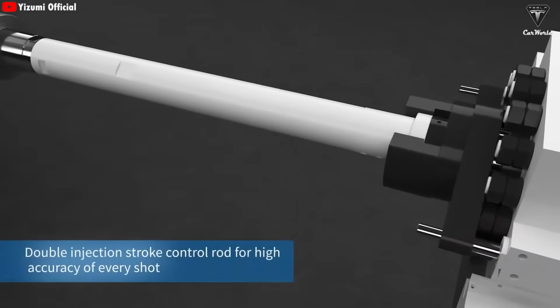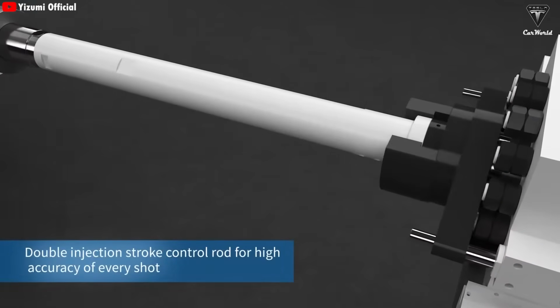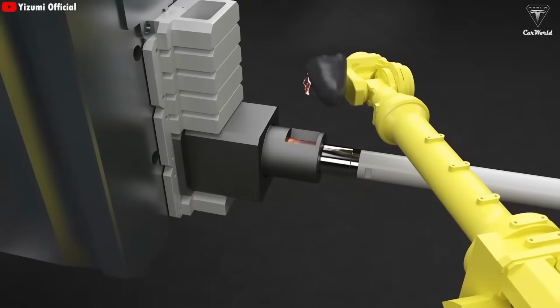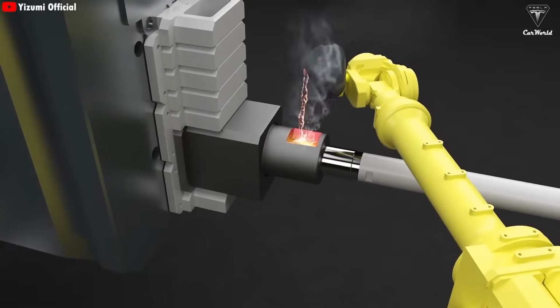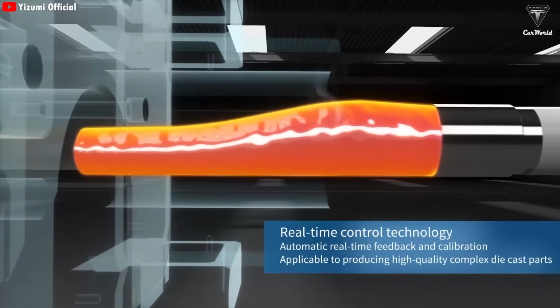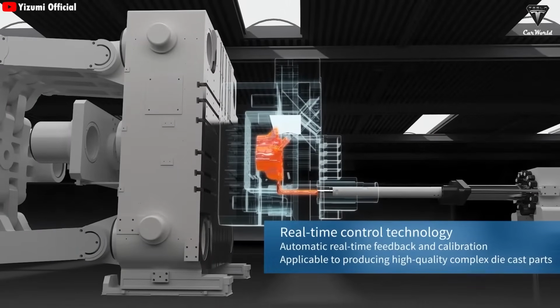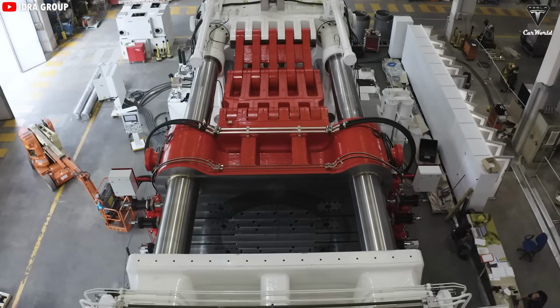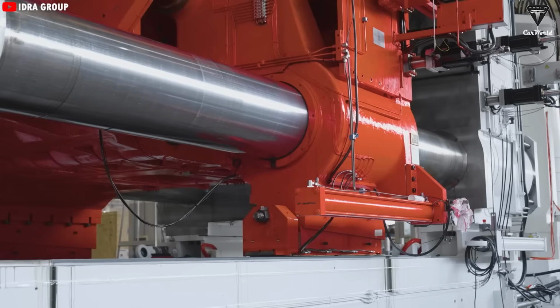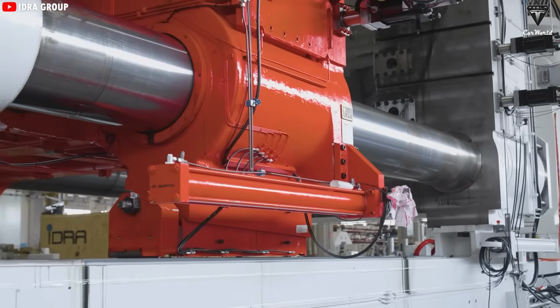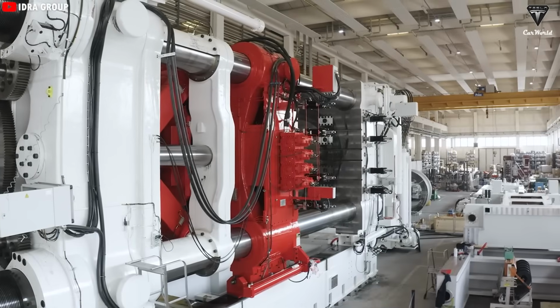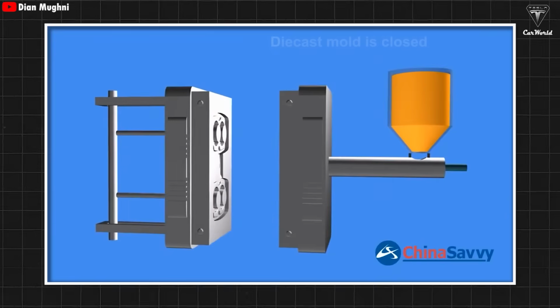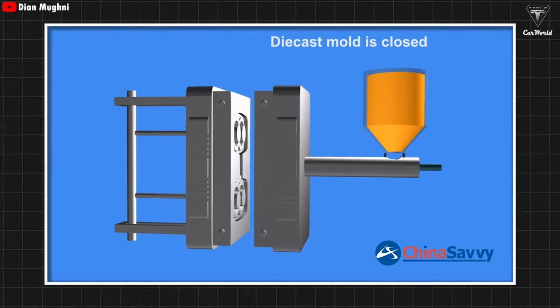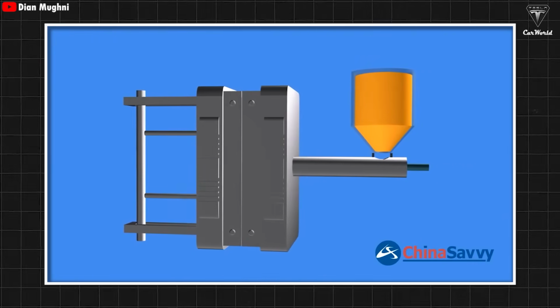If the molten aluminum is injected into the mold too quickly, there's a high risk of air bubbles forming, which would weaken the final part's strength and durability. Conversely, if the injection process is too slow, the aluminum may begin to cool before completely filling the mold, resulting in incomplete or uneven parts. That's why the 50,000-ton Giga Press casting system must operate with extremely high precision. Every movement, every second, needs to be carefully controlled. After the aluminum is injected, it remains in the mold until it fully solidifies.